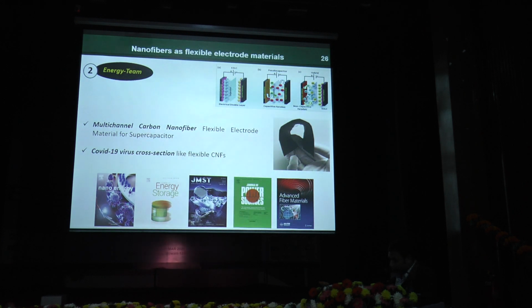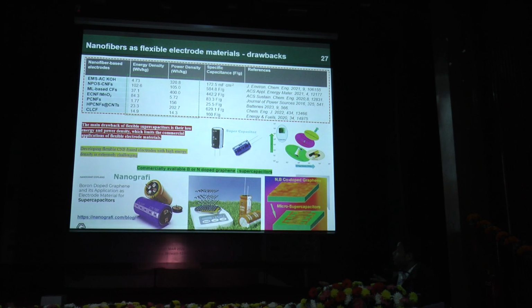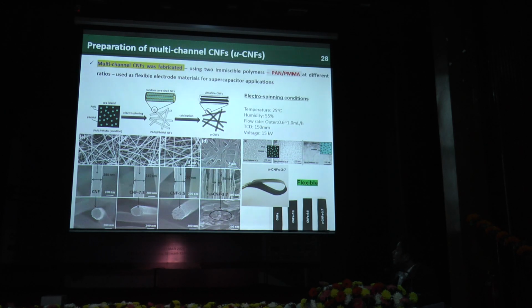And we developed electrode material for energy storage application as well. As you know, when you go for a flexible material, the power density and energy density are the challenging ones in the energy application. So we modified the electrode material to bring some unique property. This is the experimental procedure. We mixed two immiscible polymers, PAN and PMMA, and we electrospun it. Then after stabilization and carbonization, we obtained multi-channel carbon fiber.